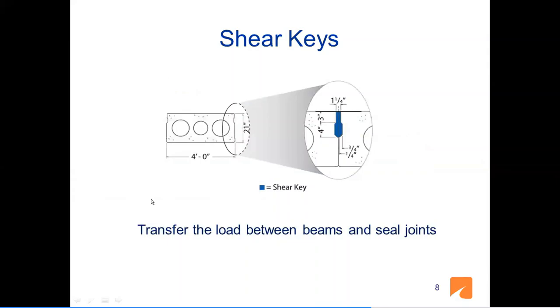Now, we use them in shear keys. Here you see a voided slab, a beam, and then next to it is another one. And here you see the shear key between them. It is a very small cross section. If you look at the top, it is only 1 1/4 inches in width, very small, and 3 to 4 inches in depth. So this is a very small section. Here they normally place grout, but they had problems with cracking and chloride penetrating through these shear keys and causing corrosion at the bottom of these beams.